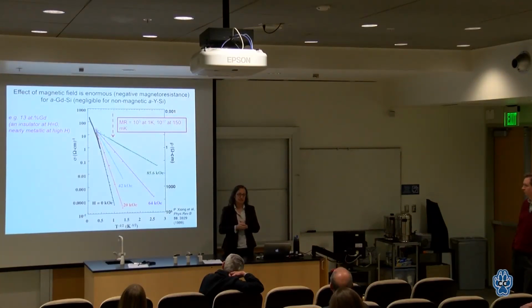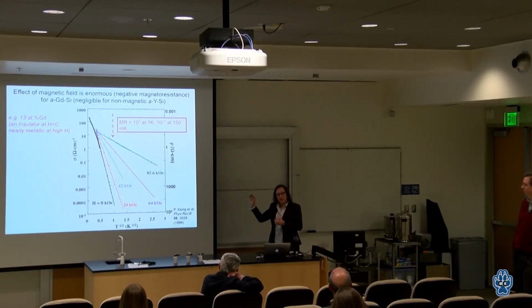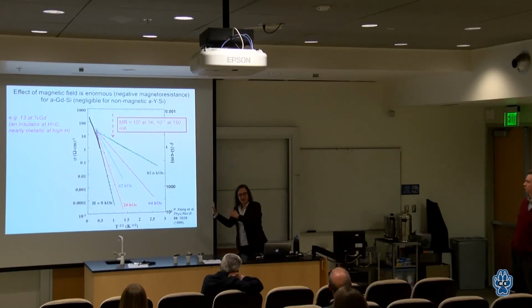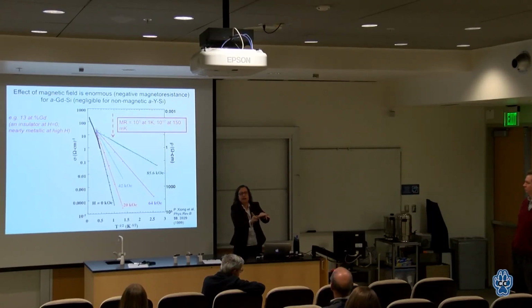The field of metal insulator physics is a competition between Coulomb effects, meaning literally the electrons negatively interacting with, repelling each other, and localization effects. So the language I'm about to use is entirely the Anderson localization language. In that framework, I'm going to start in zero field, so the gadoliniums are all pointing in all different directions. And every F electron has an S electron, which are the carriers. The S electron interacts through an SF exchange interaction, and that creates an additional source of disorder. So as the S electrons which carry the current travel, every time they meet a different direction, it's an additional form of disorder.